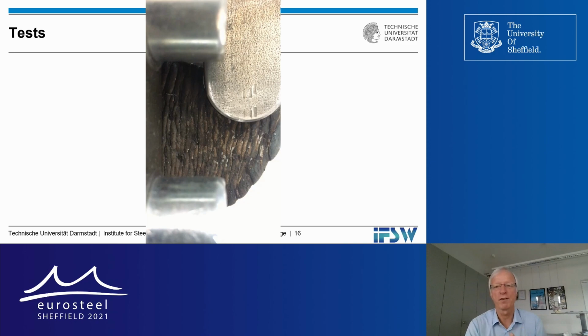And as you see in this little video, the steel behaves very ductile. So you don't get the brittle failure that you might expect if you have a welded connection, but you saw that we have a very ductile behavior, large deformations before the weld between our 3D printed hook and the flange of the column failed. That's where you expected it, on the top side where you get tension or stress. There we had failure in this case.